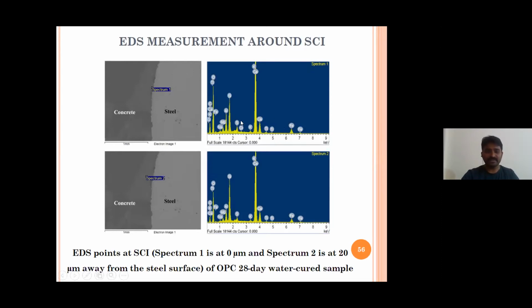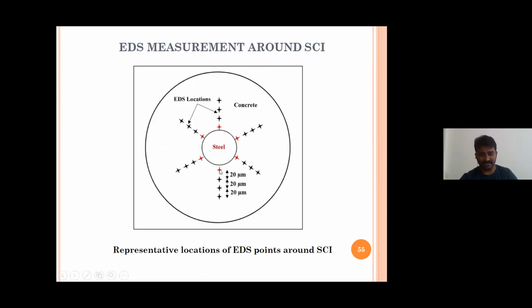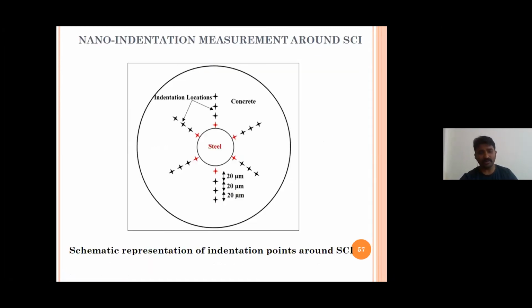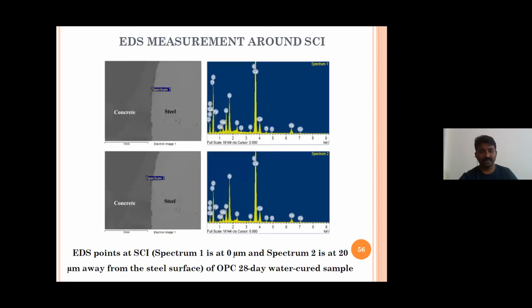Okay, so these values we obtained at different locations. For example, spectrum 1 is at 0 micrometers, and spectrum 2 is at 20 micrometers, right? This is the result for spectrum 1. This is the result for spectrum 2. So for these two, what is the difference? Likewise, we have considered 0, 20, 40 and 60 micrometers. Through this, what do I study? From this, we can identify Ca/Si ratios.